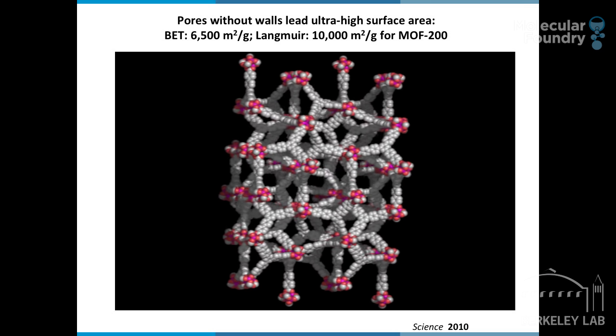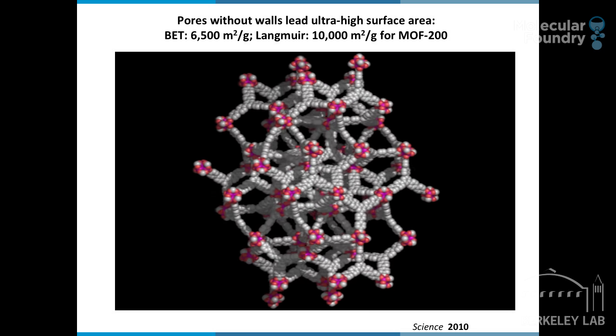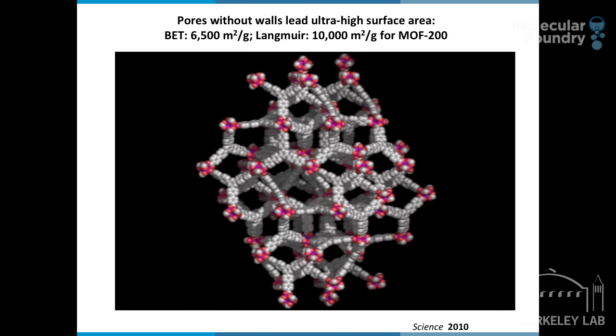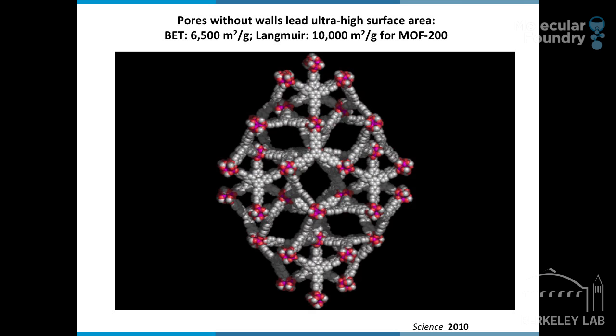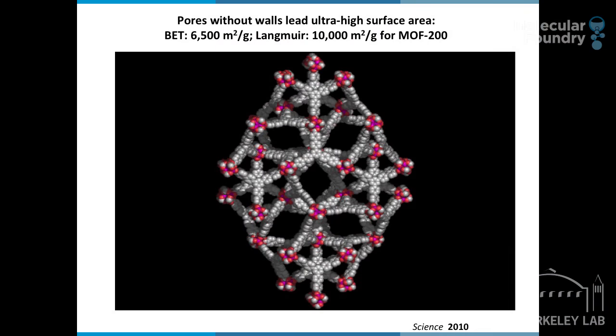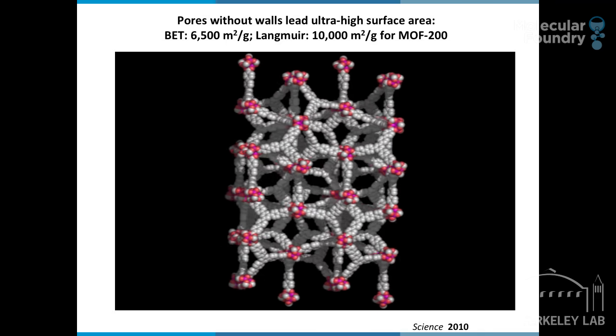Let's look at a typical MOF structure. We found from single crystal X-ray diffraction studies on gases within MOFs that everything you're looking at in a MOF structure, whether it is the multi-metal joints or the 6-membered rings or the edges, are all adsorptive sites. Essentially, one can say they're all parking spaces for gas molecules to be sitting on and compacted within the pores. Another very special thing about these structures is that they are very open. They have pores without walls, and it means that substrates, gases, and other molecules can move in and out of the pores with great facility, and the pores never really get clogged. So this, you can imagine, is a boon for applications such as catalysis and gas storage. This particular structure, MOF 200, was a record up to 2011.